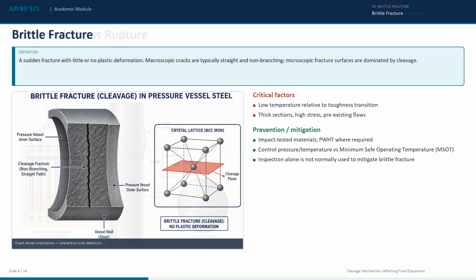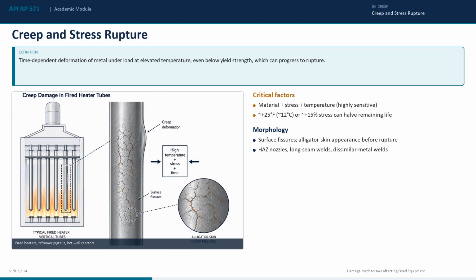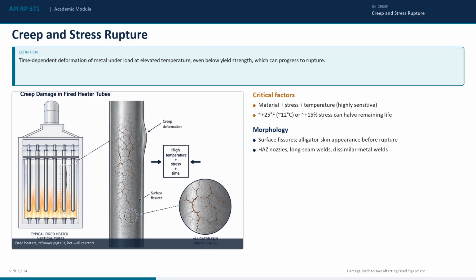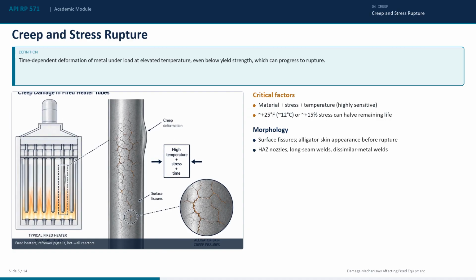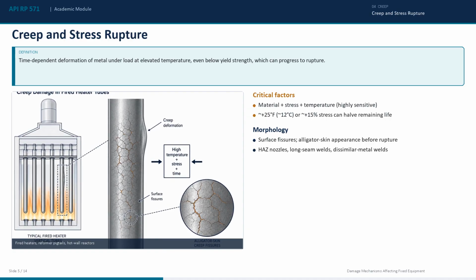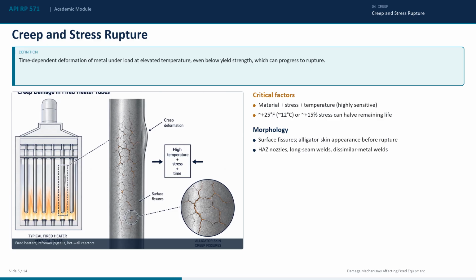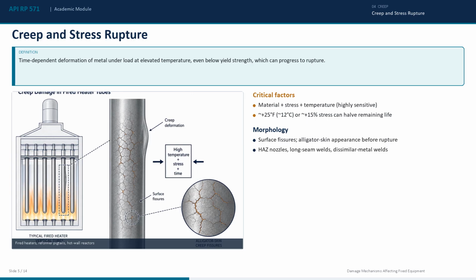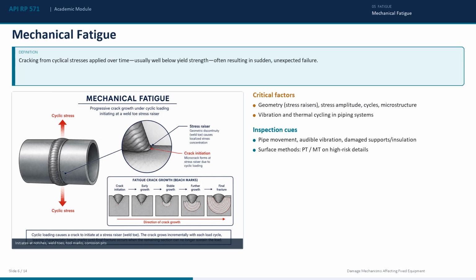Creep and stress rupture. Definition: time-dependent deformation under load at elevated temperature, even below yield strength, which can progress to rupture. About a 25-degree Fahrenheit rise, or roughly 15% more stress, can halve remaining life. Typical locations: fired heater tubes, reformer pigtails, and dissimilar metal welds. Morphology often shows alligator skin surface fissures.